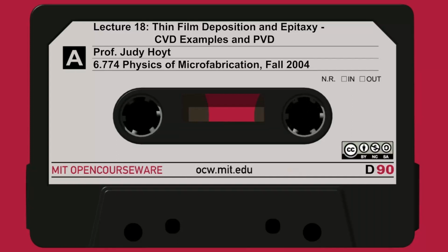It's going to be quite different. Why do we care about that? Well, polysilicon is the gate material in CMOS until we get to metal gates. Of course, metal gates are coming very quickly, but for the last 25 or 30 years, polysilicon has been the gate material. Typically, it's put down in an undoped state, and then it's ion implanted in the near surface region, and then you do a high temperature anneal, typically during the source drain anneal or maybe a separate one, in which you hope to get these dopants down from the surface all the way down to the interface with the oxide to form the gate. If I don't get all the dopants down there, you're in deep trouble.